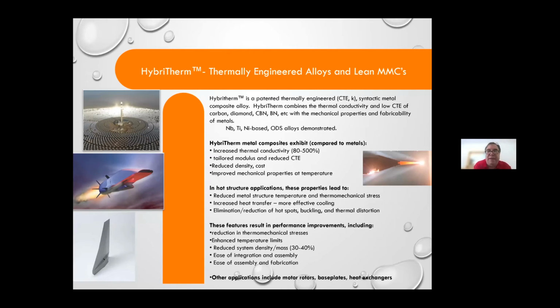Hybritherm is a patented, proprietary, thermally engineered, lean metal matrix composite, including coefficient of thermal expansion and thermal conductivity. We are producing these in niobium, titanium, nickel, and ODS, oxide dispersion strengthened, iron-based materials. And these are reinforced with high thermal conductivity and low CTE materials. They have basically the ability to add 80 to 500% increase in thermal conductivity, tailor the modulus and reduce the CTE, and reduce the density and the cost.